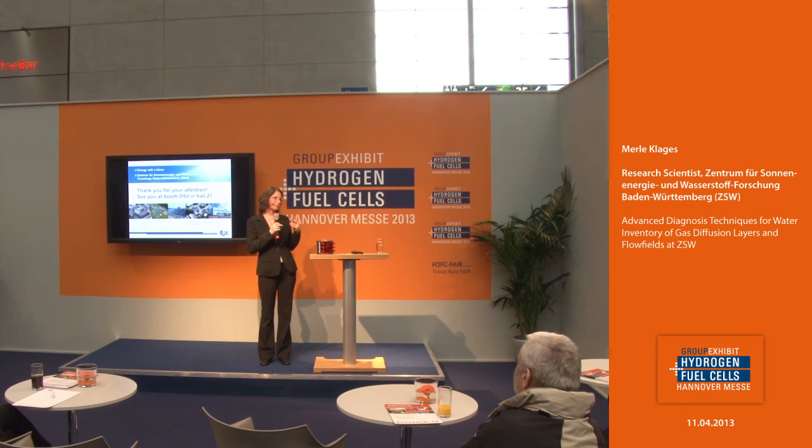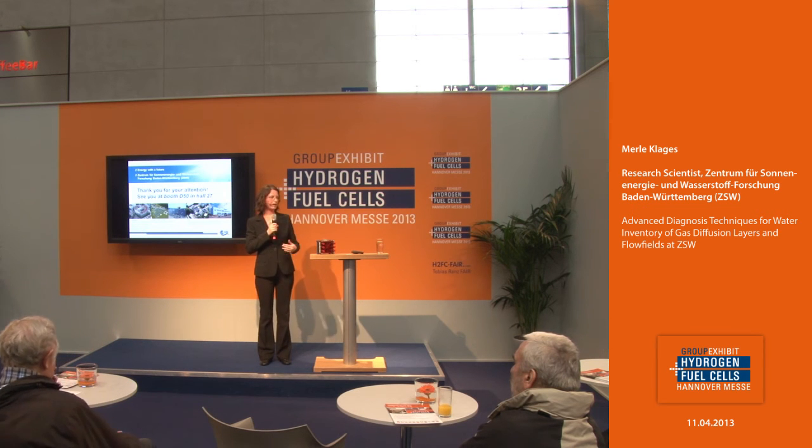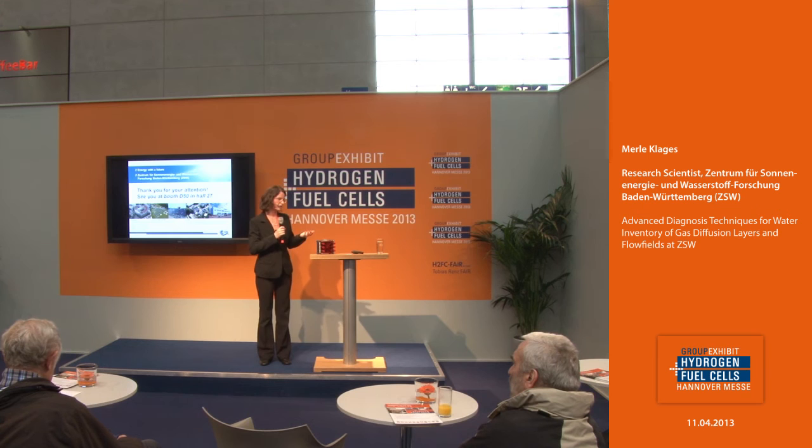Well, there are some sort of boundary conditions. If the GDL is completely filled, the fuel cell performance is quite low. But there are also several investigations about how the relative gas humidity inside the fuel cell is optimal for a good performance. If we perform the actual experiments during neutron and synchrotron radiography and tomography, we also measure the performance. For example, by impedance spectroscopy, you could correlate the resistance to the humidity.